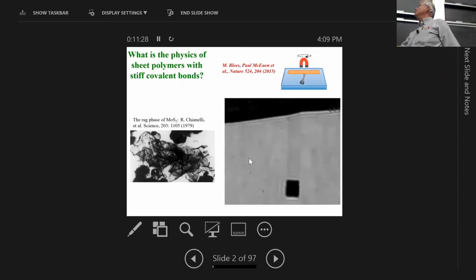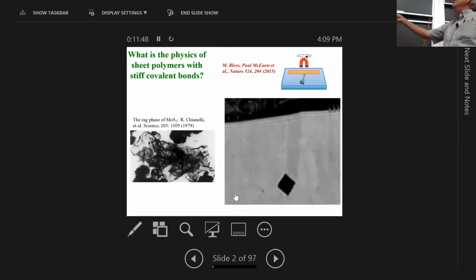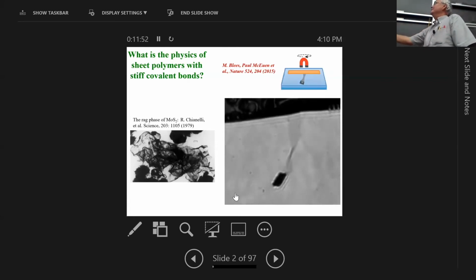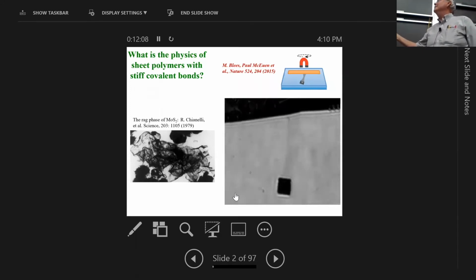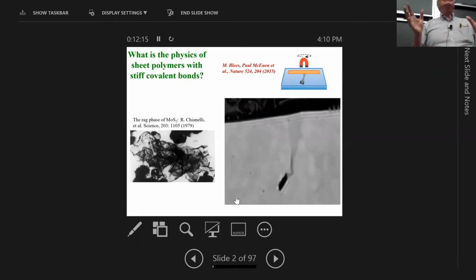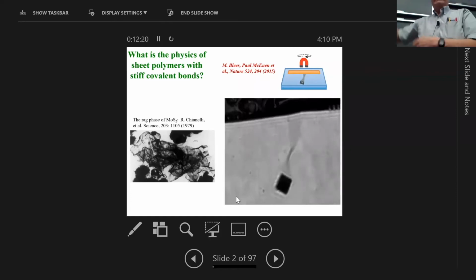And this is a very beautiful paper by Paul McEuen and Melina Blees from Cornell University, where they actually made ribbons of graphene. You can sort of barely see the graphene ribbon here. It's 10 microns across. And what I'm going to show you, if I can make this movie run, is the result of using this refrigerator magnet to activate this magnetic pad at the end and sort of torture this atomically thin object. This atomically thin object has an aspect ratio of maybe 20,000 to 1. It's 20,000 times thinner than it is wide. And it's the analog of a single molecule biophysics experiment, basically, but done on graphene in water at room temperature. So it's subject to the thermal fluctuations.